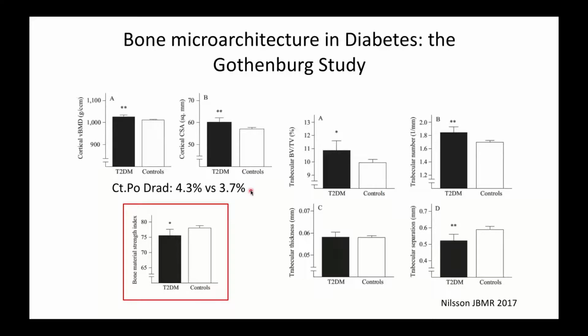And what came out of the study here, but also from the study by Farr before, of course, is that there was a significant decrease in the material strength with the microindentation, but that is not the purpose of my presentation. So as you see so far, the evidence for microarchitectural alterations in diabetes are small. If they are somewhere, they are more in the cortex, and perhaps there is increased porosity, but not always. And if it is, not to a very large extent.